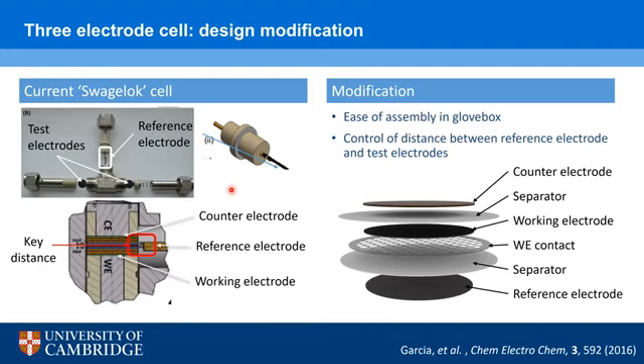Dylan mentioned reproducibility, and in terms of applying a reproducible amount of pressure when testing different cells. In this type of design, the two plungers are effectively tightened in opposition to each other, so it's quite difficult to control the amount of pressure that's applied to the cell. So the reference electrode in this design is introduced in the middle through a kind of probe-like wire, and it has a small piece of lithium attached to the end at a fixed distance from the rest of the cell,